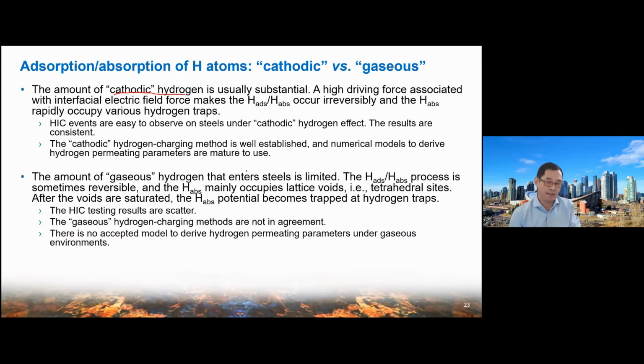But as a comparison, if the hydrogen atom is produced from the gas phase, the amount of gas hydrogen usually is limited. So sometimes the adsorption of hydrogen and the absorption of hydrogen, this process is also reversible. Hydrogen that goes inside can also go outside. After hydrogen goes into the steel, it tends to occupy the lattice voids first. And after the voids become saturated, hydrogen is concentrated in the other hydrogen traps, such as dislocations, grain boundaries, something like that.